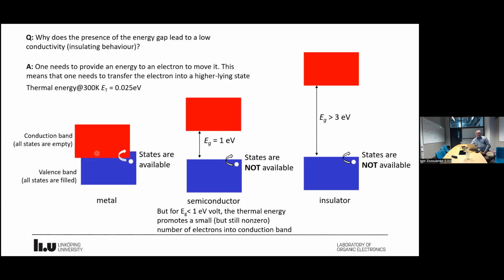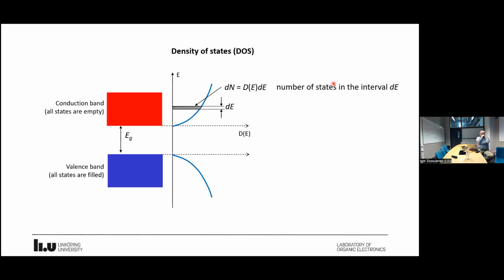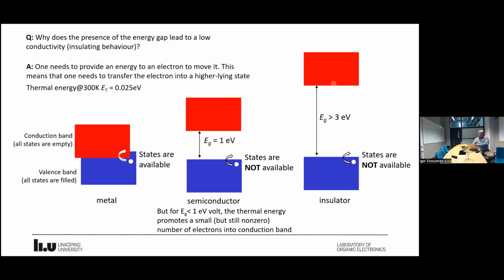However, for the case of the metal, look here. Here are filled states in the valence band, but the conduction band is overlapping with the valence band, and in the conduction band there are a lot of empty states. So this thermal energy is enough to move electrons from the valence band into the conduction band, and then electrons can move inside the crystal. For the case of an insulator, the gap is so large that the thermal energy is not enough to fill the conduction band, so practically your conductivity will be equal to 0. Okay, so this was the classification of conductors, semiconductors, and insulators based on the band structure.